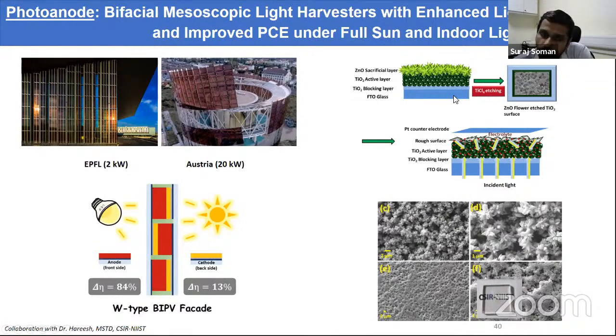In conventional electrodes, what we normally have is a semiconductor with around 20 to 30 nanometer particle size, which can hold the maximum amount of dye molecules. On top of that, conventionally we put scattering layers with particles around 400 nanometers, and the purpose is to realize backscattering. But when you use those 400 nanometer particles, you compromise your transparency, so you won't be able to make transparent bifacial solar cells. So what we have done here is introduce a new technique where we create certain imprints on the surface of the TiO2 through a controlled etching mechanism using different zinc oxide structures. That resulted in a bifacial photovoltaic device, which can harness light from both sides, the front side and the back side, with almost comparable efficiencies.